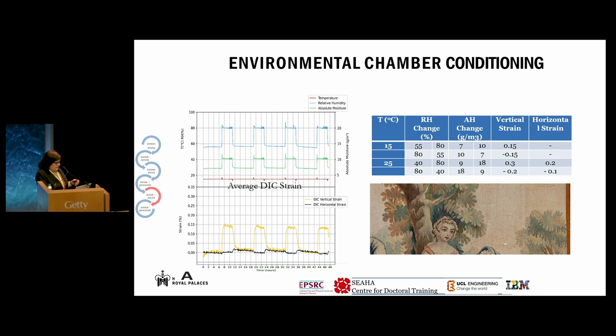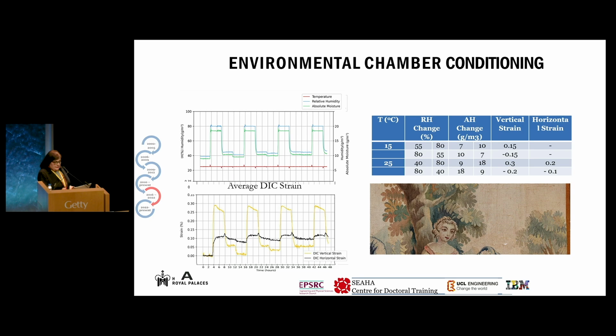Results from the experiment at 25 degrees centigrade showed higher strain variation compared to the 15 degrees. RH increasing from 40 to 80% caused 0.3% vertical strain, while when the level of RH drops back to 40, the vertical strain is around 0.2%. For the horizontal strain, an increase of around 0.2% is observed when RH changes from 40 to 80, and when it returns back to 40, it was less than 0.1%.